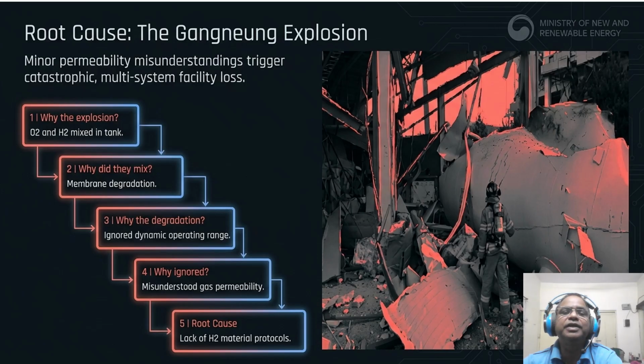Follow the 5 whys staircase on the left. Why the explosion? Oxygen and hydrogen mixed in the tank. Why did they mix? Membrane degradation. Why the degradation? Because the team ignored the dynamic operating range. Why was it ignored? Because they misunderstood gas permeability. The root cause was a lack of specific hydrogen material protocol, and the operational impact is a 50 million US dollar loss and a total loss of public trust.